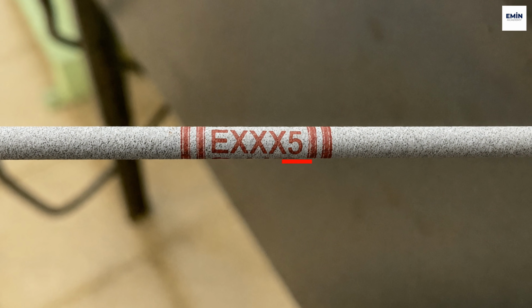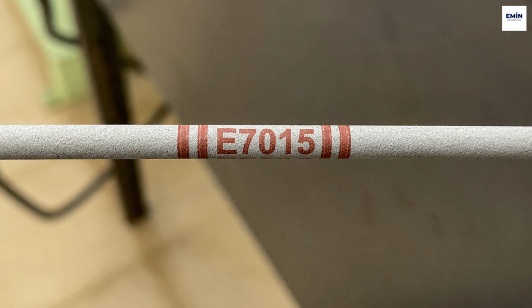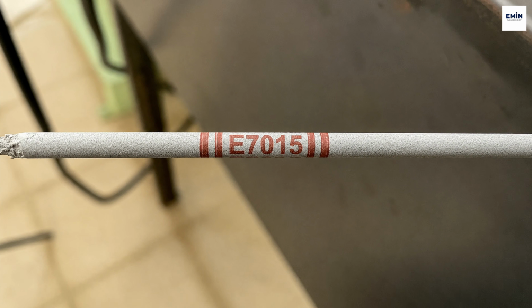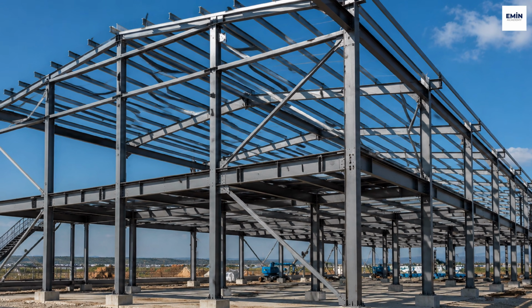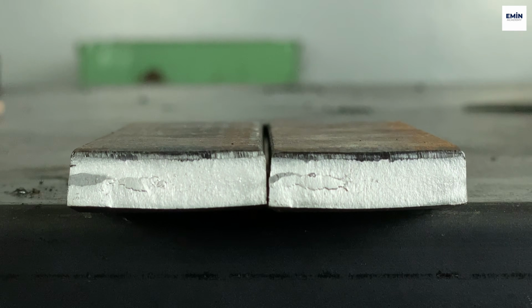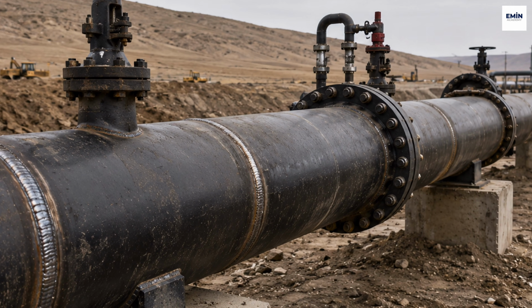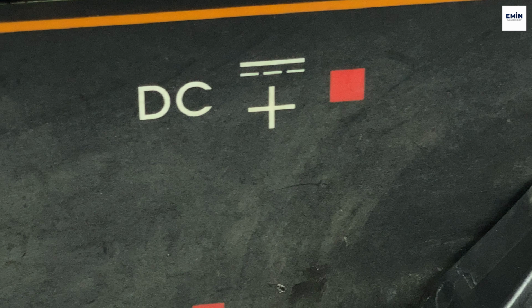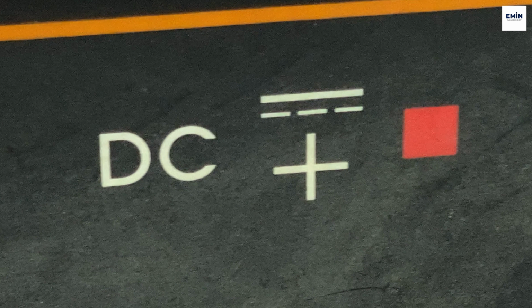5. Basic coated electrode. The E7015 electrode is an example. It creates a tougher and stronger weld metal. It's generally used for high-strength jobs, thick materials, and critical welds. It is suitable for direct current electrode positive polarity.